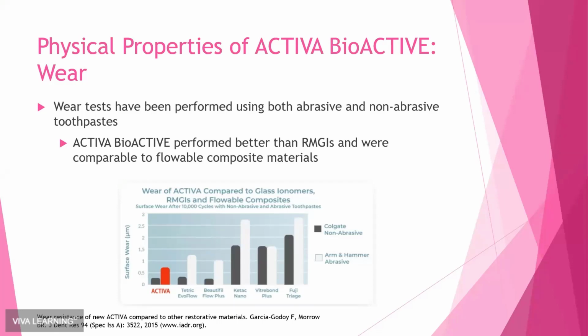So when we're looking at this graph, the bars on the left are using the non-abrasive toothpaste. Those are in the dark gray. And then the bars that are on the right that are the white, that's using the abrasive toothpaste, or the Arm & Hammer. And you can see that over 10,000 cycles of toothpaste, which is a lot of brushing, a lot of potential wear, the product that has the least amount of wear when compared is the Activa restorative material.